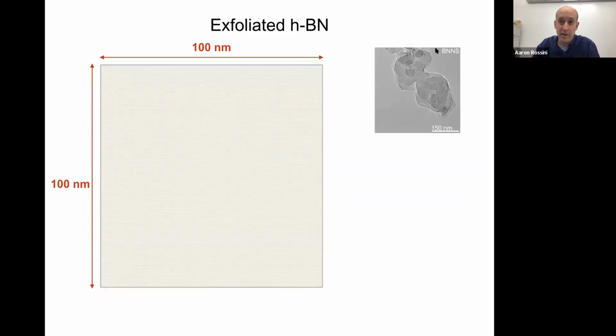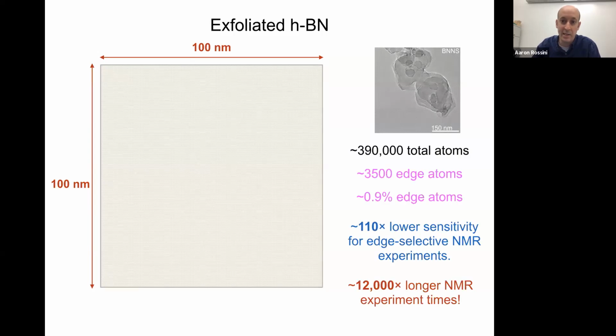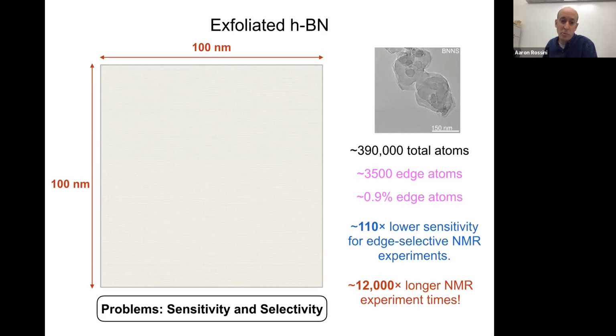Now, if we look at our TEM image here of the exfoliated nanosheets, we actually have sheets that are more like 100 nanometers by 100 nanometers. So if you repeat that calculation, only about 0.9% of the atoms are going to be found on the edge of the sheet. So you're going to have 110 times lower sensitivity and 12,000 times longer NMR experiments if you do an edge selective NMR experiment. So really we have two problems, sensitivity and selectivity.